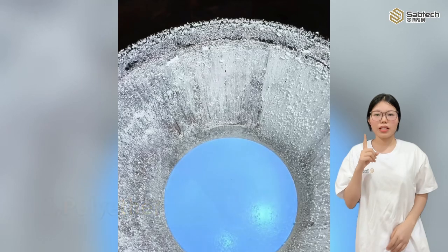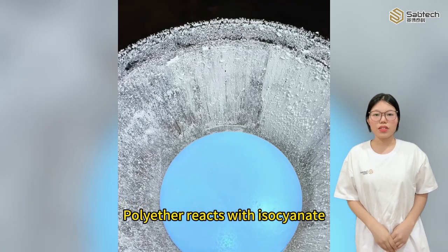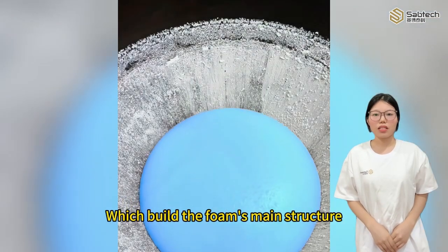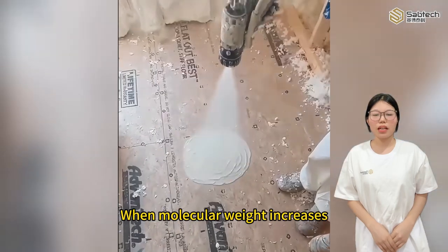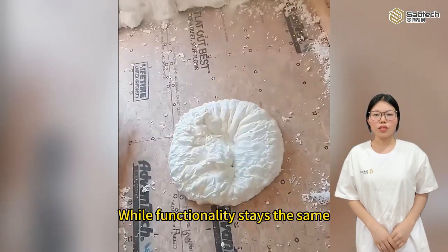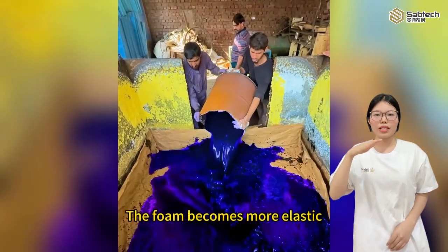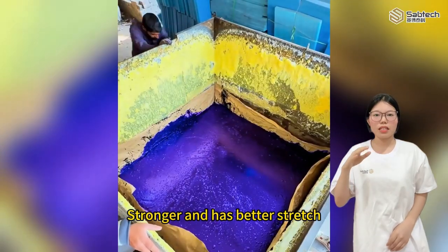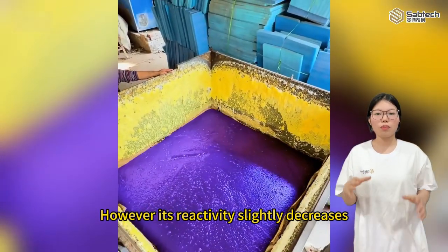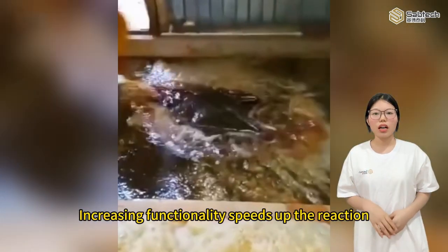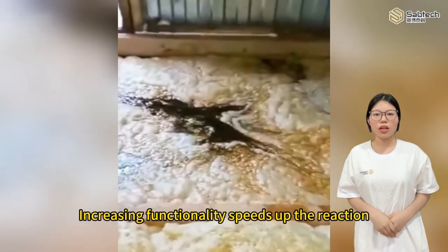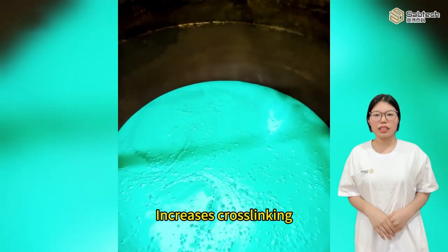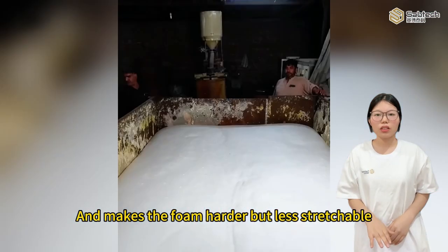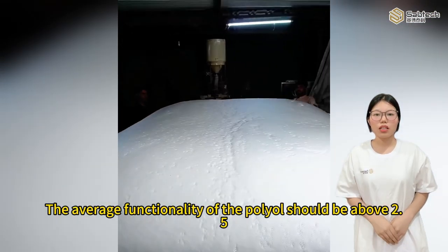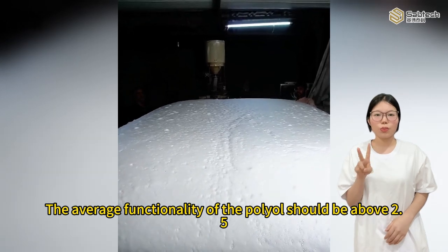First, polyether. Polyether reacts with isocyanates to form urethane bonds, which build the foam's main structure. When molecular weight increases while functionality stays the same, the foam becomes more elastic, stronger, and has better stretch. However, its reactivity slightly decreases. When the equivalent value stays the same, increasing functionality speeds up the reaction, increases crosslinking, and makes the foam harder but less stretchable. The average functionality of the polyol should be above 2.5.